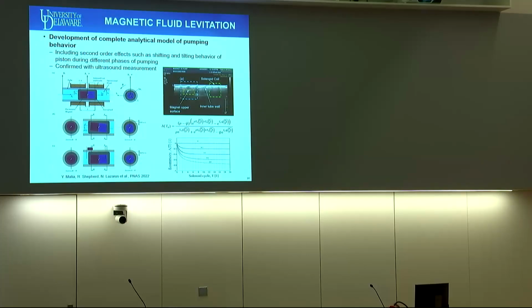Using this, we developed a complete analytical model of the pumping behavior. And particularly, we're able to capture some really interesting behaviors, where you get almost a snowplow type effect, where the permanent magnet tilts somewhat as it goes back and forth through the channel. We were able to model and understand this and even confirm it. We went up to the Cornell Vet School and used their medical ultrasound to see and measure the permanent magnet going back and forth within the channel to demonstrate that we had a good understanding of the magnetic piston within this pumping system.